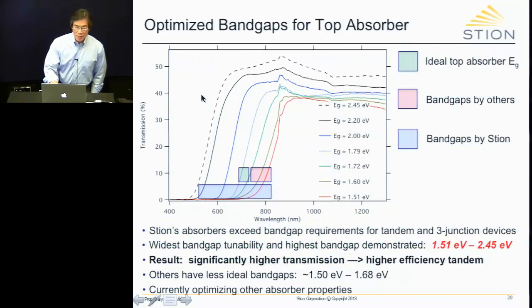So this shows how we optimize the band gap for the top absorber. These are the transmission spectra for the top absorber. So you can see basically this is below the band edge, and then as you approach the band edge, the transmission drops. So the band gap happens to be where this drops off. If you look at where the ideal top absorber needs to be, it's really within this region right here. And if you look at what others have been able to demonstrate, it's right in this region here. And it just makes it to where the top device has to be.